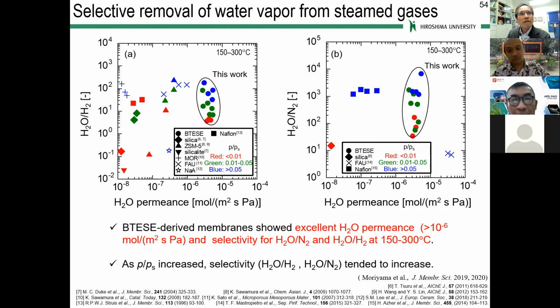Now here is a trade-off of water vapor over hydrogen, and water vapor over nitrogen. Okay, so this organosilicon membrane is plotted over here and over here, right? Other types of membrane, like a Nafion type polymer membrane, are now typical water removal membranes. The Nafion polymeric membranes are plotted over here. Organosilicon membranes show very high performance even at high temperature, 150 to 300 degrees C, with a permeance higher than 10^-6, with a selectivity around 100 over hydrogen and over nitrogen, more than 1,000.